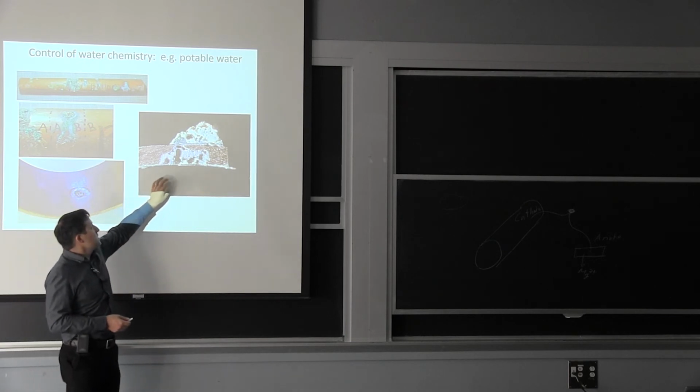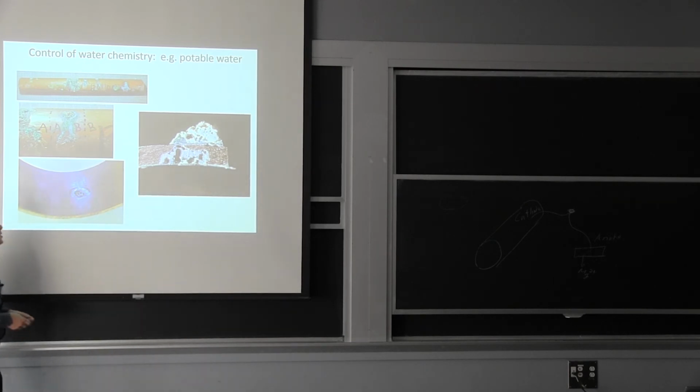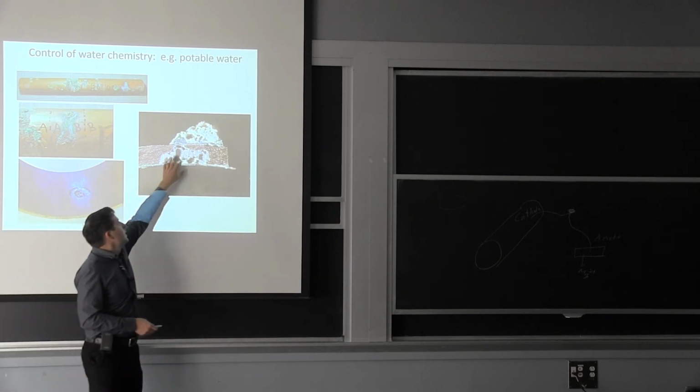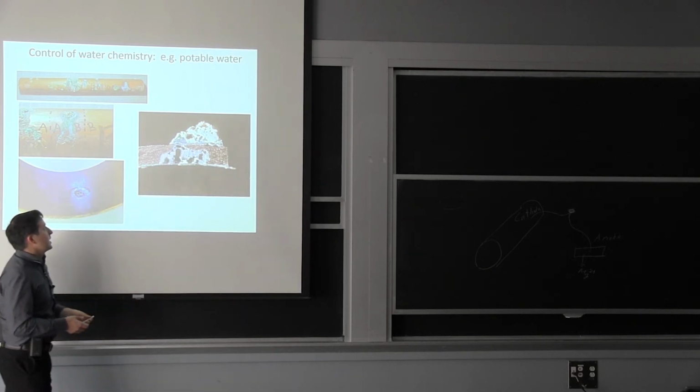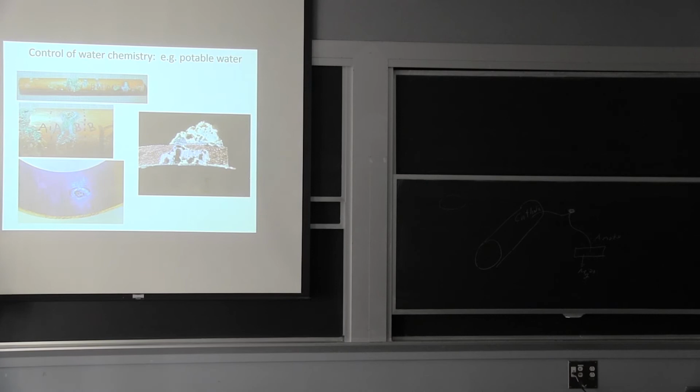Now, what was interesting that I have seen on a number of these systems is if you look at the outside of the pipe, it's the copper pipe up there, and it still holds water without dripping. So in the process of the water getting through the hole, when it gets to the outside, it's high temperature, and all the deposits in the water will just solidify and it can clog the hole.